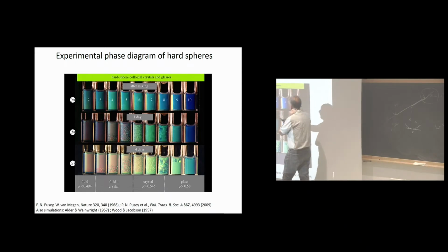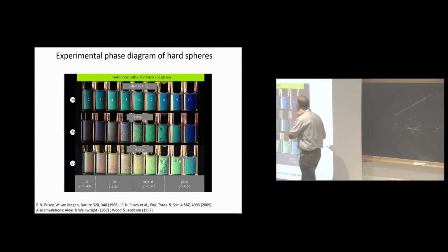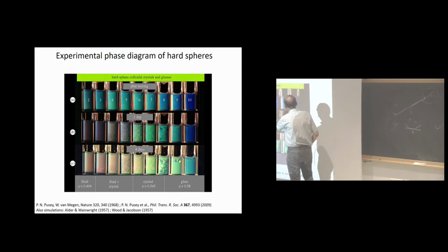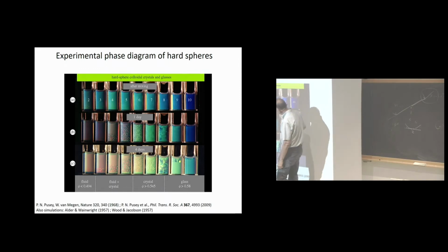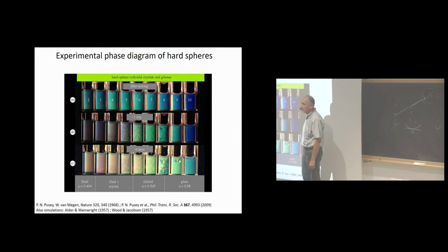So they started preparing PMMA suspensions in different volume fractions. And so you increase volume fraction from number 1 or 2, whatever is there, to number 10. And so you see what's going on after 1 day and after 4 days. And what you clearly see is from the Bragg peaks here, the evolution of crystalline phases. And then as you keep on increasing the volume fraction, at some point, again, they are lost. Okay? So there is a way now to define the phase diagram.